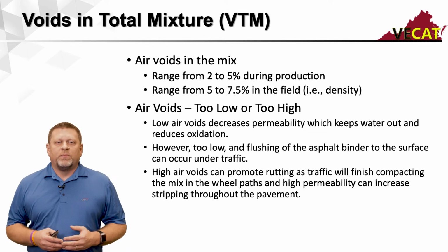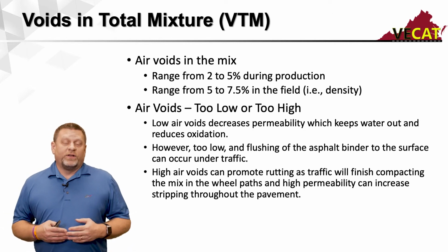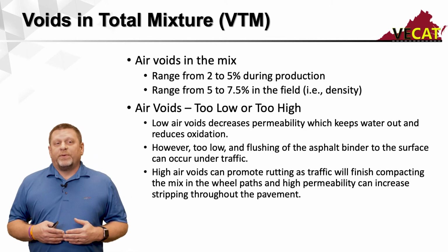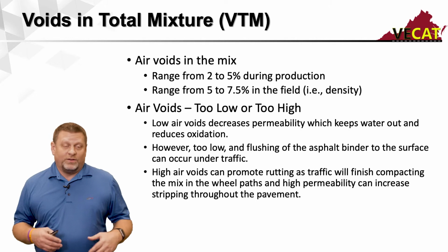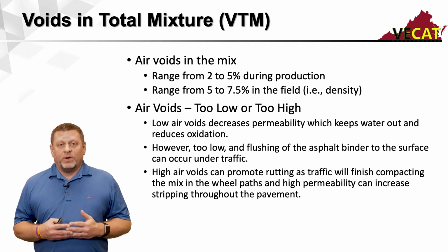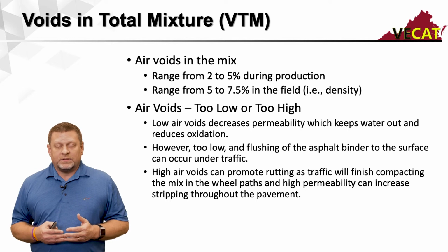High air voids can promote rutting. If we don't get good densification of our mix when we're placing our mix, what's going to happen is once this mix is opened up to traffic, the wheels of the traffic are going to continue to compact it into wheel paths. Then we're going to end up with rutting in these wheel paths.